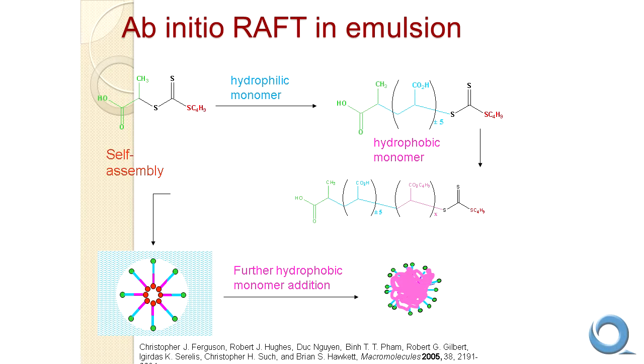And then, in this case, I'm showing it with acrylic acid as the ionic monomer. We can stop this process, we can collect this polymer, and we have an active living polymer that we can then initiate and polymerize further. And so we initiate that in a second step of the polymerization, where we use a hydrophobic monomer. In this case, I'm showing butyl acrylate as the hydrophobic monomer. And we can then add a second block to the polymer.